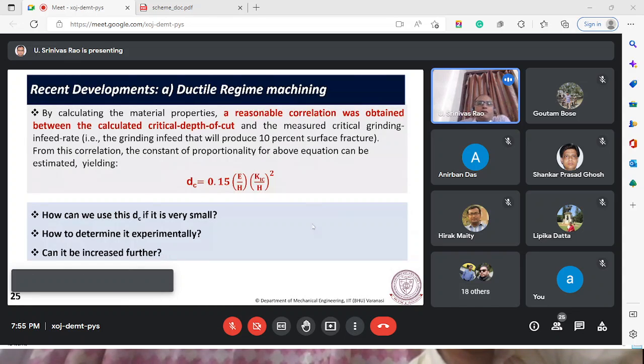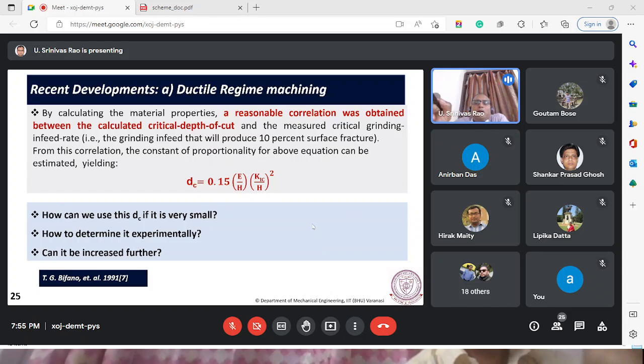Now, from this work, what we have obtained is that there is a possibility of ductile regime machining, and to achieve that, we want to know the critical depth of cut. If we can go for machining or grinding in-feed rate below that, then we will achieve ductile regime machining. So first knowing this is important, then keeping the depth of cut below this.